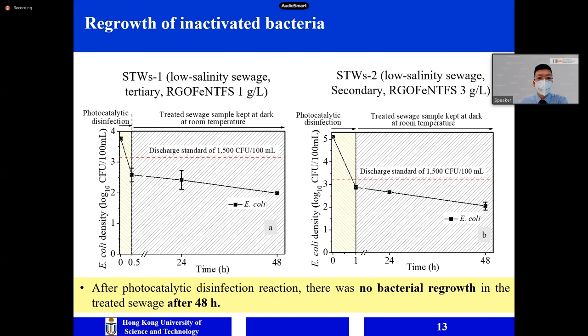For the regrowth test, we further performed this test for the inactivated bacteria. For the first and second types of sewage samples, we got a promising result: we just kept the treated sewage in the dark for 48 hours after the reaction. We can see that the E. coli density was stable in both types of sewage sample. That means no bacterial regrowth by using this technology in the treated sewage after 48 hours.